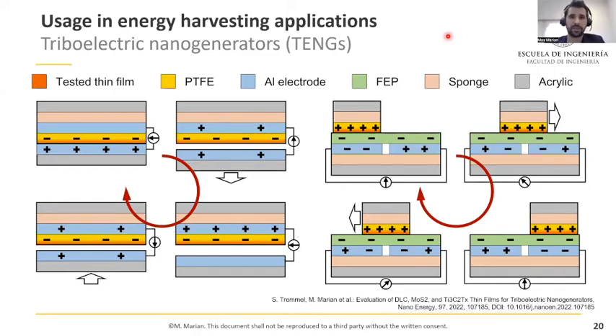But despite the great progress in TENGs regarding the configurations, the materials, and so on, their durability under sliding motion especially still is one of the major concerns and is directly related to the wear behavior of the contacting surface. And some surface engineering approaches, such as the deposition of wear-protecting thin films that fulfill the electrical requirements, also help to meet the conflicting objectives, so to reach a certain electrical output, but also to ensure the durability of the coatings, of the TENGs.